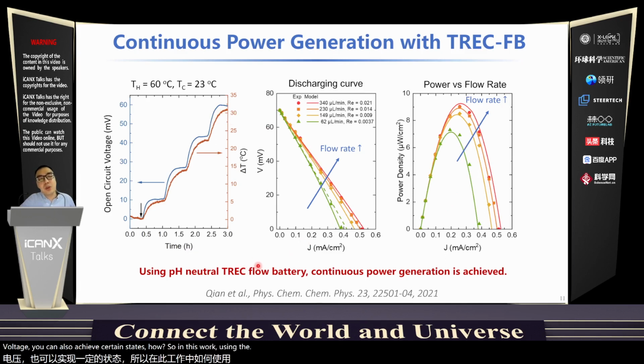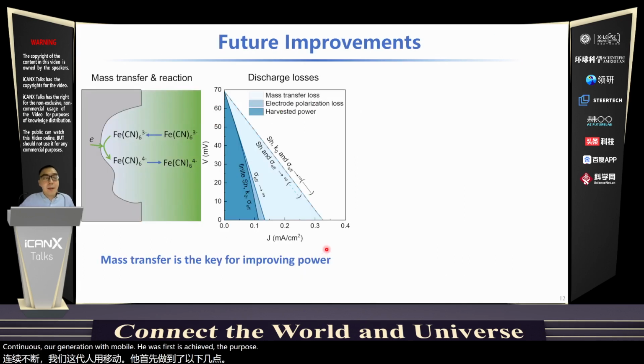So in this work, using the pH neutral flow battery, continuous power generation with low-grade heat is achieved for the first time. Future improvements are still to be done, especially considering power density. We did some analysis and found that the mass transfer loss is the major mechanism of power loss. The reason is that we need to supply the reactants from the bulk solution to the interface. Only then can we do the charge transfer between the electrode and the electrolyte. So if the mass transfer process is slow, you will have degraded power. So in the next step, we are going to look into ways to design a hierarchical porous structure of the electrode to enhance the mass transfer.